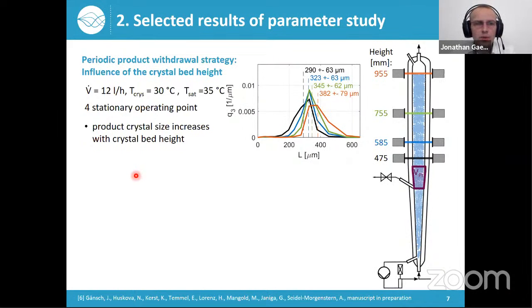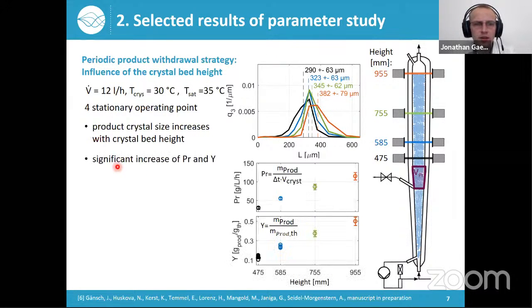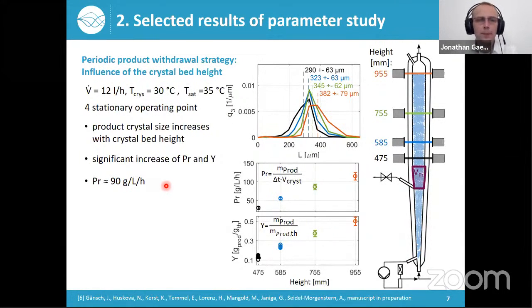But which is more important and was also more surprising is the significant increase of the productivity and the yield. Starting now from our reference strategy, 30 to 40 grams per liter per hour, we were able to double or even triple our productivity and yield just by changing the position of these photosensors. And here I want to highlight the quantity. Even without optimization, we already could observe productivities up to 90 grams per liter per hour, which is far above the before mentioned benchmark of 20 grams per liter per hour.